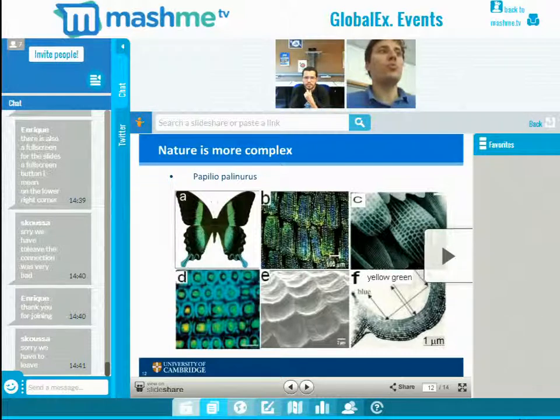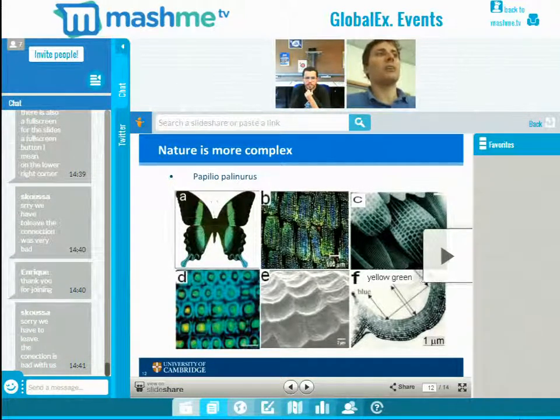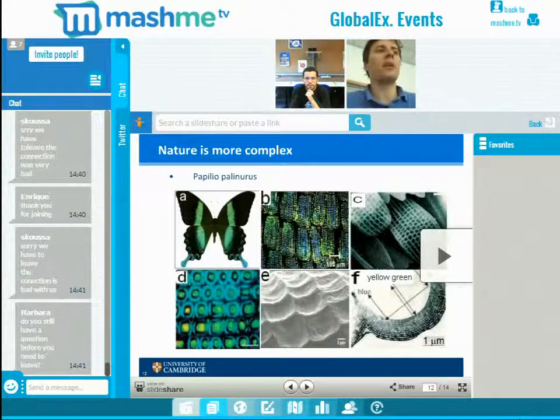You can zoom in a bit more with the optical microscope, but it's really hard. So this is already borderline what you can resolve with the optical microscope. You can do a bit better, but as I said before, the wavelength of visible light is between 300 or 400 and 800 nanometers. So you can't really resolve spots that are smaller than 400 nanometers.